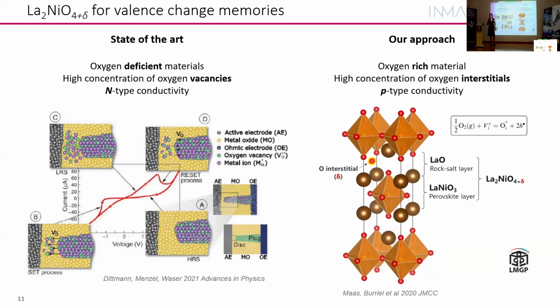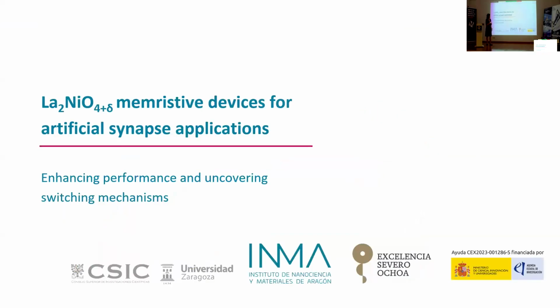But what we did, and we started this work already many years ago, is a totally different approach. So we chose this lanthanum nickelate material, which is oxygen rich. So instead of having oxygen vacancies for the oxygen diffusion, we have oxygen interstitials, and it's a P-type conductor. Okay, and now, after this introduction, I will move to really show you some of the most important results we've obtained during these years.